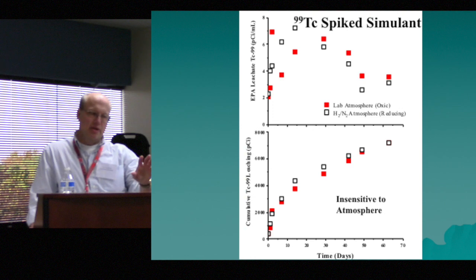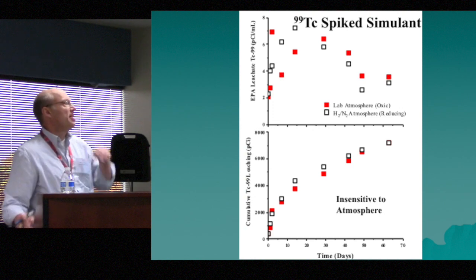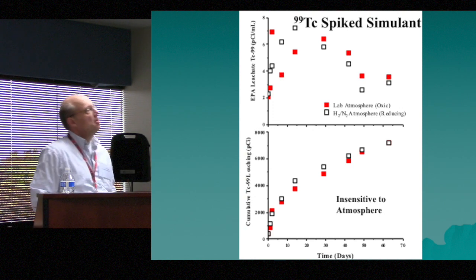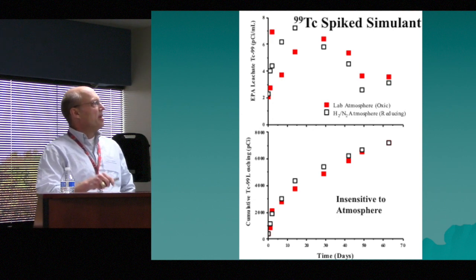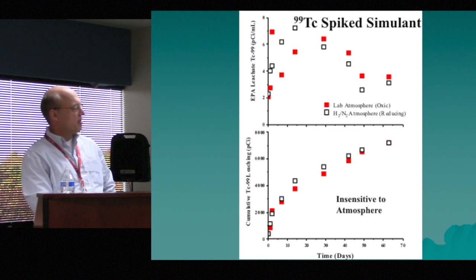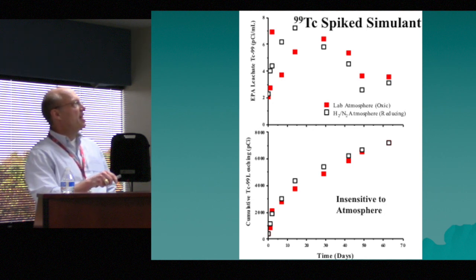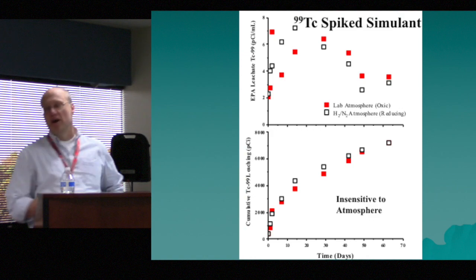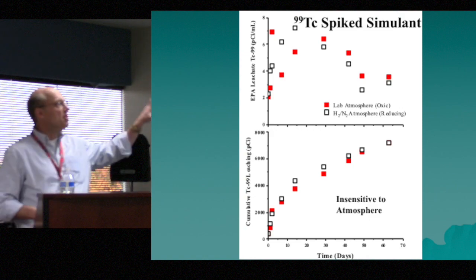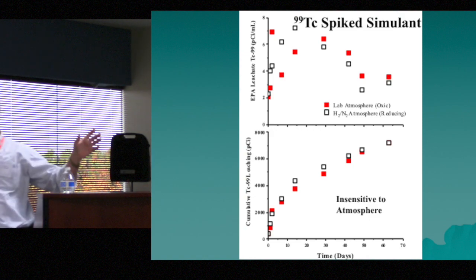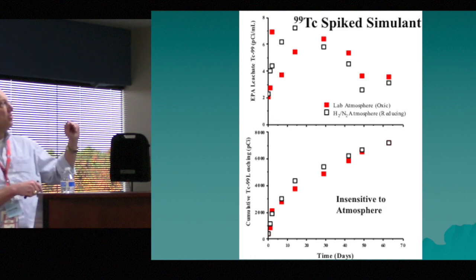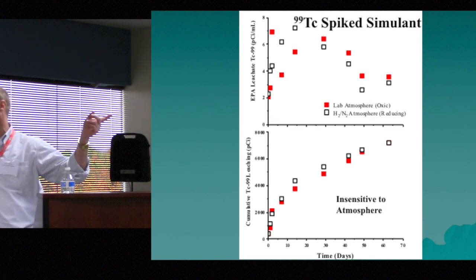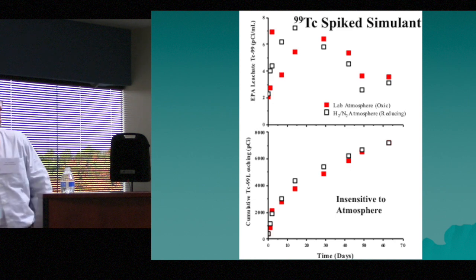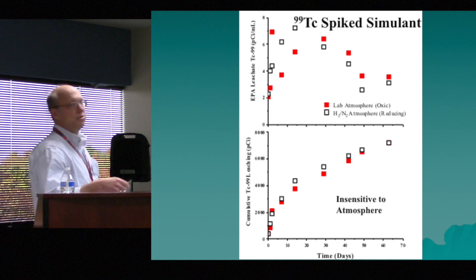So this is just a little bit of the data for Tc-99 spike simulants. This is the type of data you generate up here. This is over time. I know it's very hard to see in the back. So going over the 63 days, this is Tc-99 in solution under the 2 extreme environments. Under the atmospheric conditions, oxic samples, and then under what I would consider reducing samples because of the high hydrogen level in the solution.